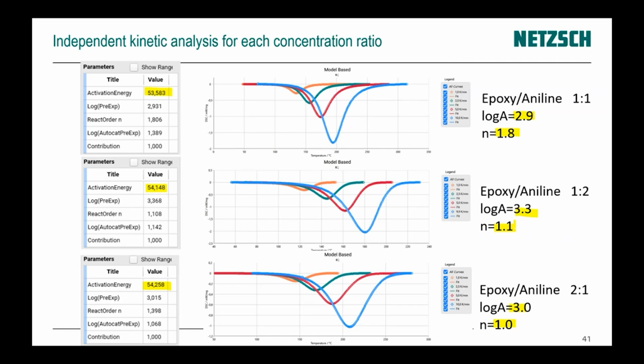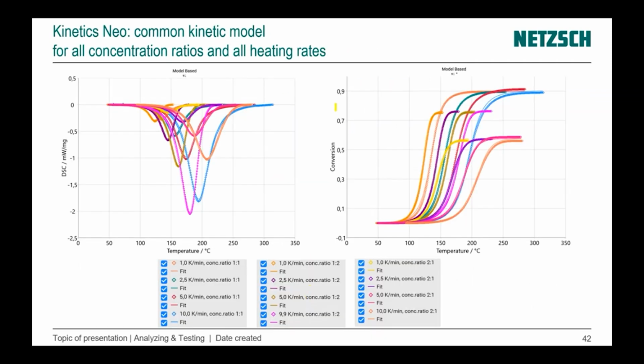And now we can just use the new version of our kinetics and make not a separate analysis for each ratio, but a total analysis for all ratios and for all heating rates. Now we have all 12 curves with the ratios 1 to 1, 1 to 2, and 2 to 1, and for all heating rates from 1 to 10 for each concentration ratio, and we have one model which can describe all curves with different heating rates and different concentration ratios of our reactants, epoxy and aniline.